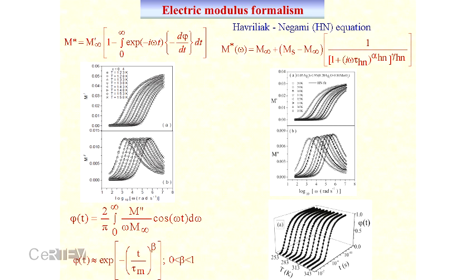But what I would like to state here is that the exponent beta in the Kohlrausch-Williams-Watts (KWW) function can give us an idea about the nature of the distribution of relaxation times. Here beta is always less than 1. For our selenide system it is of the order of 0.5 or 0.4, depending on composition, which indicates the relaxation is strongly non-exponential. Therefore, in every glass, the relaxation is strongly non-exponential because of the strong distribution of relaxation times, which arises from the distribution of the potential landscape in glassy materials because of their disordered nature.